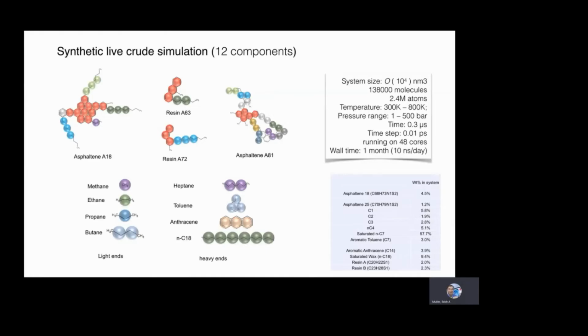Both resins and asphaltenes are polynuclear aromatic-based molecules, which, at least the latter, the asphaltenes, have the tendency to precipitate out of solution if the conditions of pressure and temperature are the appropriate ones. And this precipitation is usually a concern for production of oils, and is something that is, in general, of interest to avoid.